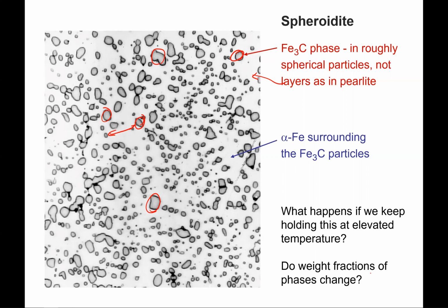And the weight fractions, again, do not change. And the longer that we hold at this elevated temperature, the larger these particles become. So ultimately, the system would be happy if there was just one big cementite particle, because that would minimize the surface area of the particle relative to the volume that it contains. Of course, as the particles get bigger and bigger, the increase in their size starts to become slower and slower as the diffusion paths between particles increase.